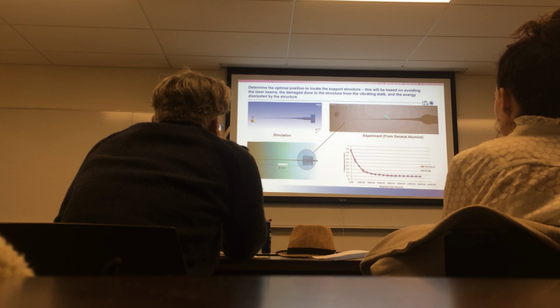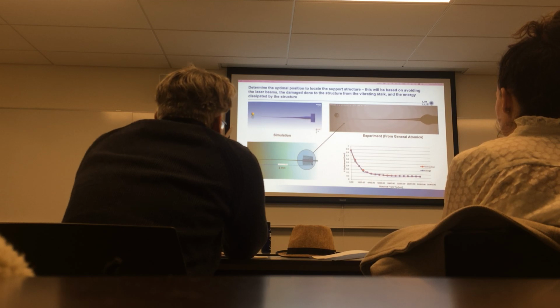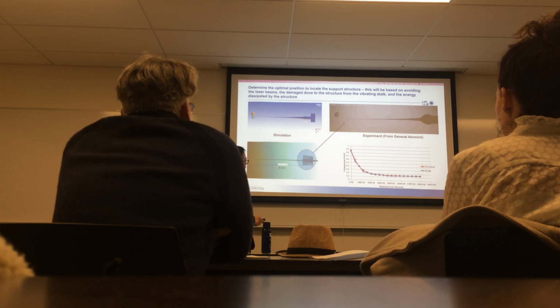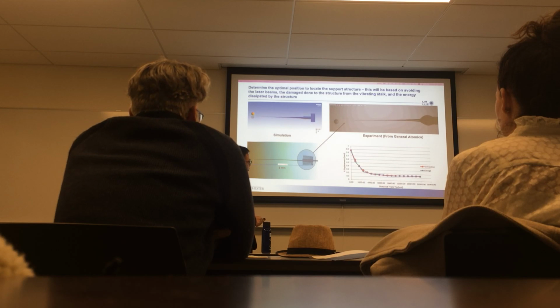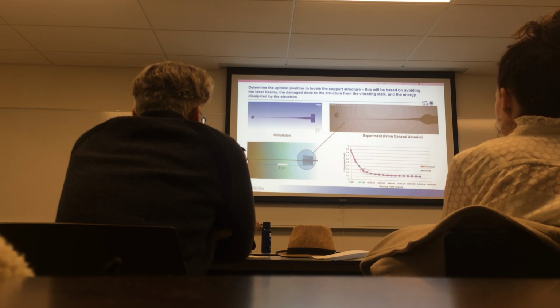It's a shaking form experiment from General Atomics, and I also use the simulation to simulate the vibration process. You can see these two images perfectly match each other. And the data is very similar to each other too. Depending on this plot, we figured out this area is the best position to locate our support structure.